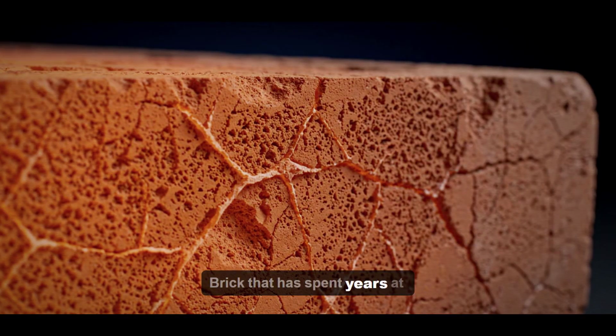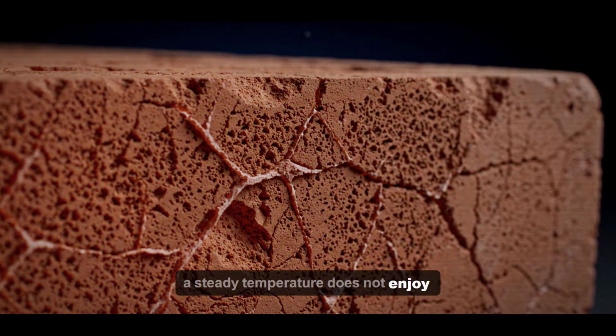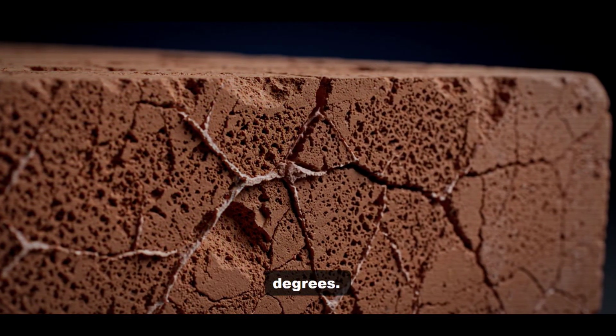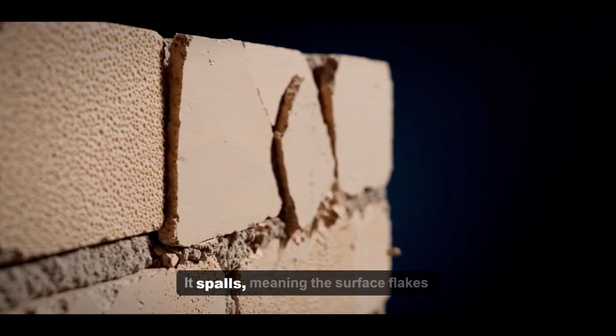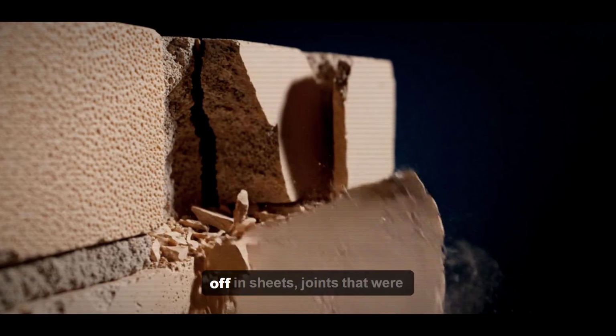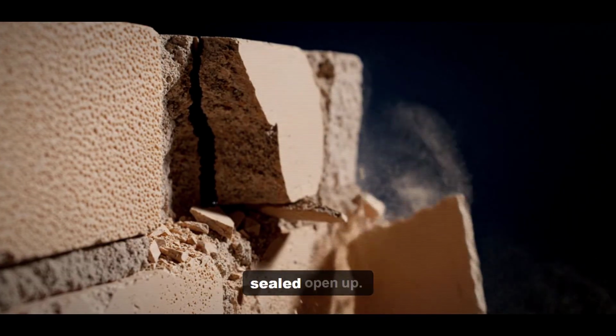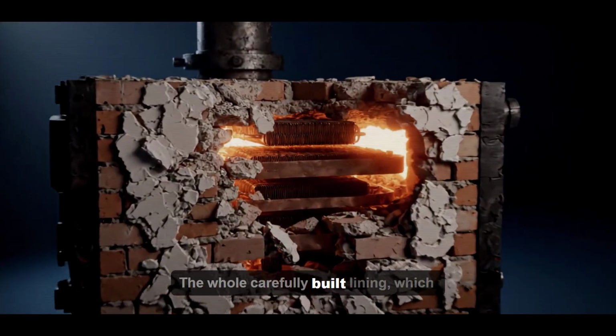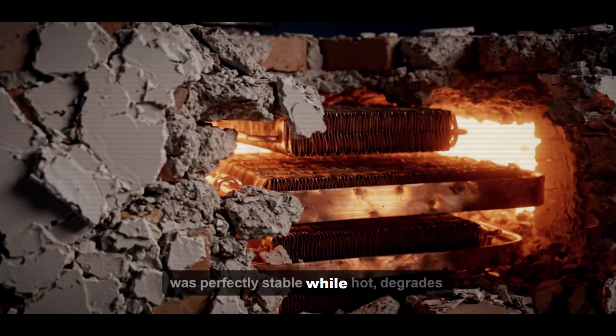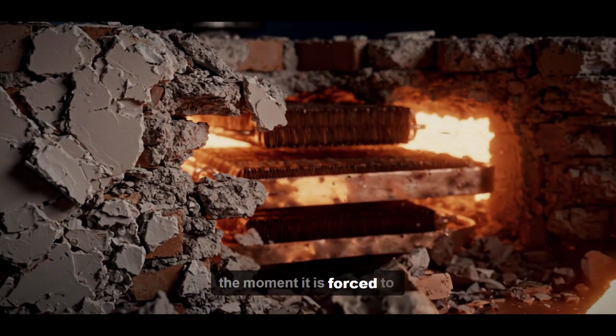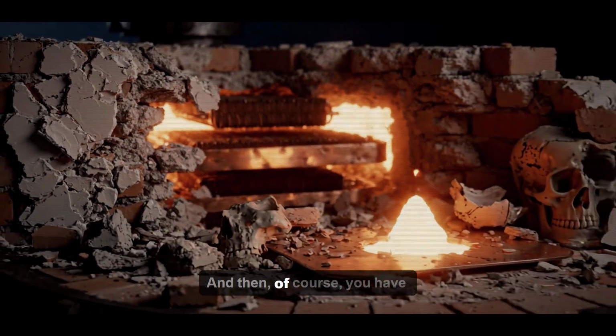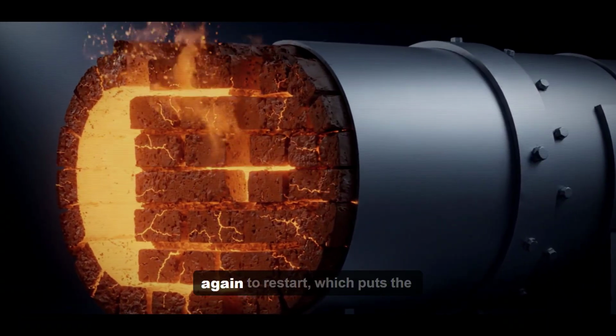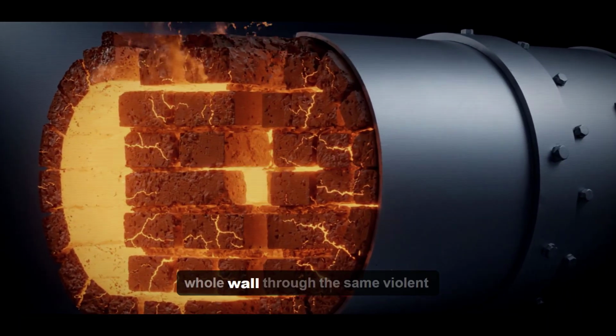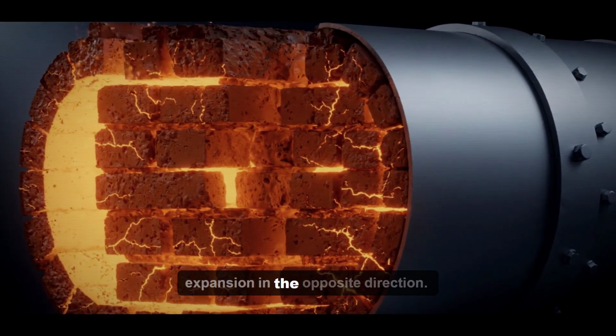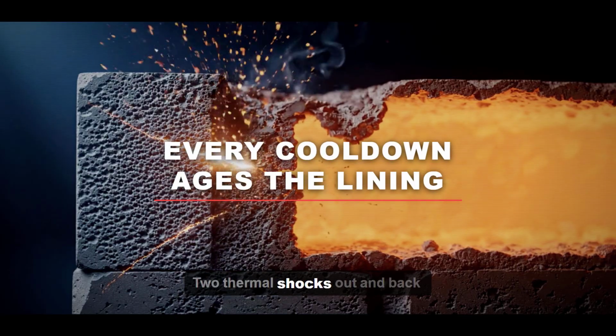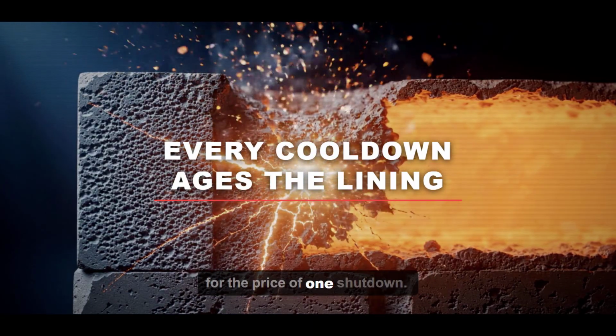Brick that has spent years at a steady temperature does not enjoy being dragged down through hundreds of degrees. It cracks, it spalls, meaning the surface flakes off in sheets. Joints that were sealed open up. The whole carefully built lining, which was perfectly stable while hot, degrades the moment it is forced to change temperature. And then, of course, you have to heat it all back up again to restart, which puts the whole wall through the same violent expansion in the opposite direction. Two thermal shocks, out and back, for the price of one shutdown.